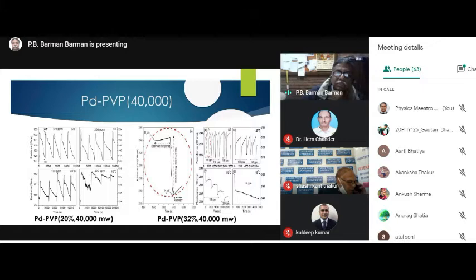This part is termed practically the electronic response. After that, there is a swelling of nanoparticles as the hydrogen gets absorbed by the particles, and ultimately the resistance drastically drops - this is termed the geometric effect. After that you put off the hydrogen, and as you put it off, again there is a recovery. This is the main sensor characteristic we got in our sensor devices.